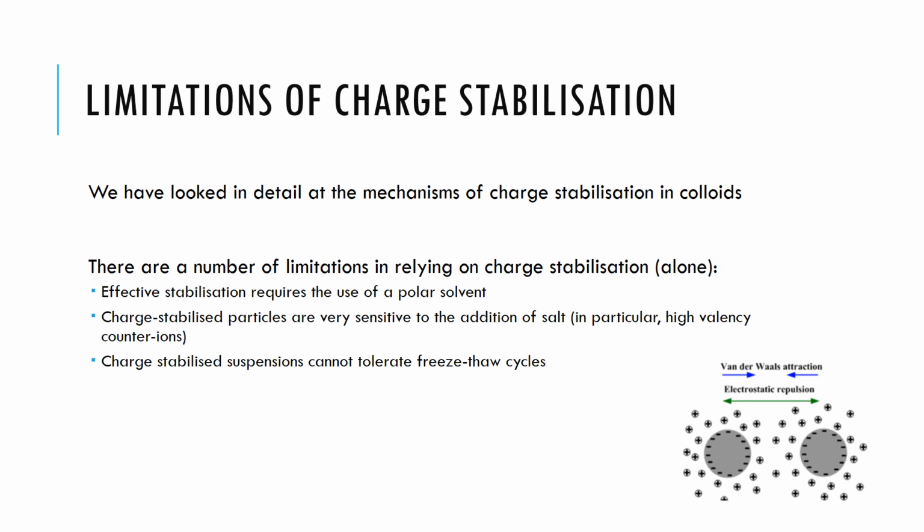If we want to rely on charge stabilization, we've got to use a polar solvent. We've got to use something like water. Charge stabilization doesn't work so well if you have a non-aqueous system, so if you have a solvent that's an oil. Particles that are charge stabilized are very sensitive to the addition of salt. They will aggregate in the presence of too much salt.